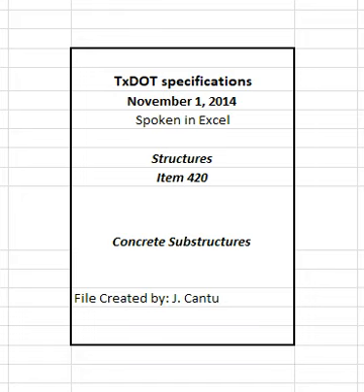Make construction joints square and normal to the forms unless otherwise required. Use bulkheads in the forms for all vertical joints. Thoroughly roughen the top surface of a concrete placement terminating at a horizontal construction joint as soon as practical after initial set is attained. Thoroughly clean the hardened concrete surface of all loose material, laitance, dirt, and foreign matter, and saturate it with water. Remove all free water and moisten the surface before concrete or bonding grout is placed against it. Ensure the surface of the existing concrete is in a saturated surface dry condition, SSD, just before placing subsequent concrete.